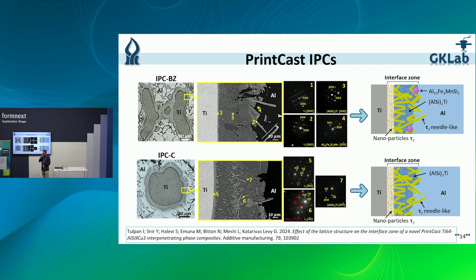Interestingly, we see that there was an extra phase that formed in the BCC lattice in the upper area. These polygonal phases form in the aluminum cast alloy whenever it cools down at a slow cooling rate. And since they formed in the BCC lattice but not in the simple cubic, we can understand that the choice of lattice structure affects the formation of these phases. We can understand that since the BCC lattice structure has a larger surface area than the simple cubic, it prevents the extraction of heat from the area in the vicinity of the interface, since the lattice structure is made out of titanium and it conducts heat very poorly. And this allows for the formation of this extra phase.